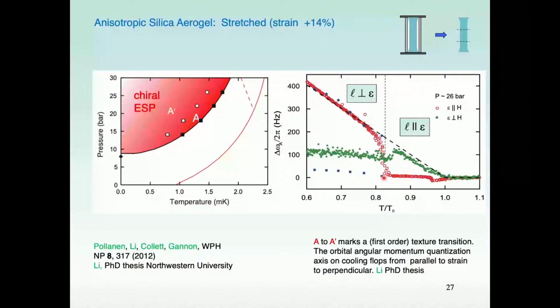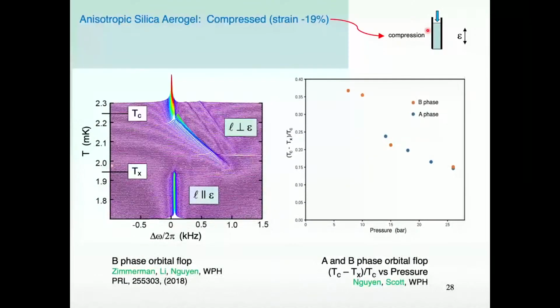Now, it's also possible to compress the aerogel, which is kind of the opposite, as far as strain is concerned, to produce a perhaps surprising result: the phase diagram becomes the B phase. It stays the B phase, but it's an anisotropic environment. And the frequency shifts that you can measure in that B phase show, on decreasing the temperature, an onset of frequency shifts to the right here. And then bingo, there's something happening at a temperature Tx. It's very similar to the behavior that was observed in the A phase for a stretched aerogel.